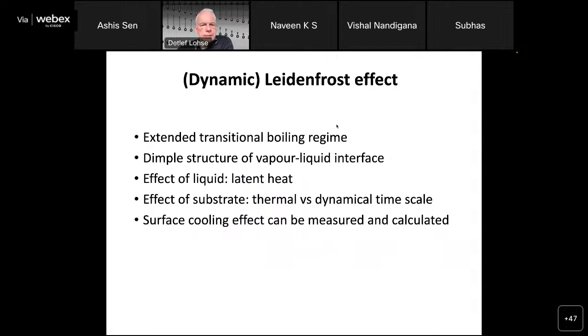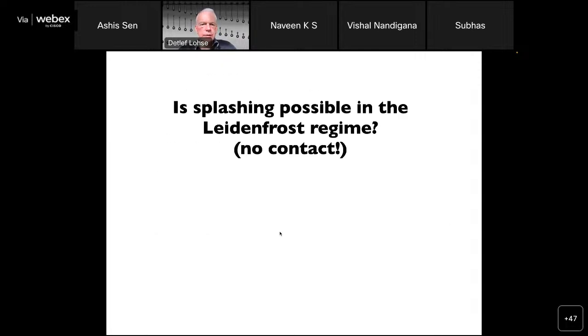So let's summarize on this dynamic Leidenfrost effect. We have an extended transitional boiling regime. We get this dimple structure. We studied the effect of the latent heat and the effect of the substrate and also the effect of the surface cooling due to this droplet. And this can be measured and calculated.